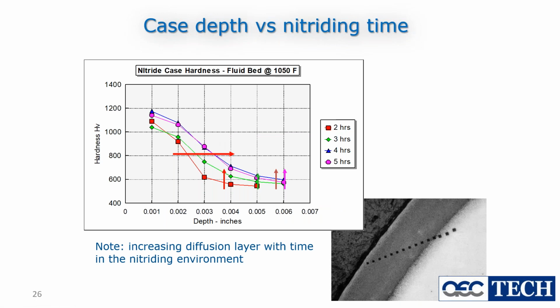And here is an example of how nitriding progresses. These are curves of hardness going from the surface in. You can see how it's done here, little micro indenters. Depending on the size, at the surface the little pyramid being knocked into the surface is a much smaller hole than the pyramids being knocked in here. You measure the size of the pyramid, and that tells you how hard the steel is in that position.